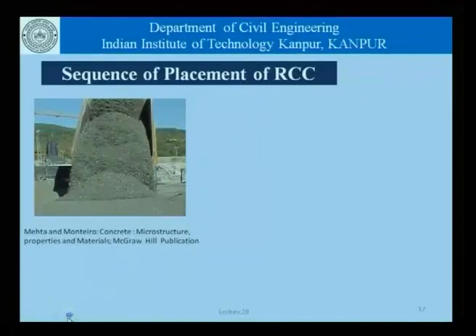This special compaction method necessitates proper care in all other steps: material selection, proportioning, and determination of properties. There is a set of pictures that will give us an idea of what roller compacted concrete is all about. Here we see concrete being dumped at a site using a tipper. The concrete looks more or less like moist gravel — it is very stiff, zero slump concrete, very different from normal concrete with a slump of 8 to 10 centimeters.